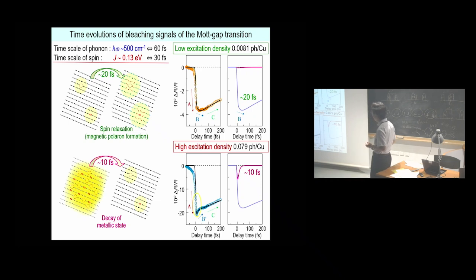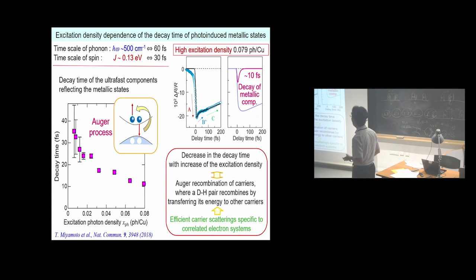For the high excitation density, we also extracted the ultrafast component by the fitting analysis, which is shown here. Its decay time is about 10 femtoseconds. This time is attributable to the decay time of metallic state. Here we plotted this decay time as a function of the excitation photon density. The decrease in the decay time with increase of the excitation density is characteristic of Auger recombination of carriers, where a doublon-holon pair recombines by transferring its energy to other carriers. Such efficient carrier scattering processes would be specific to correlated electron systems.